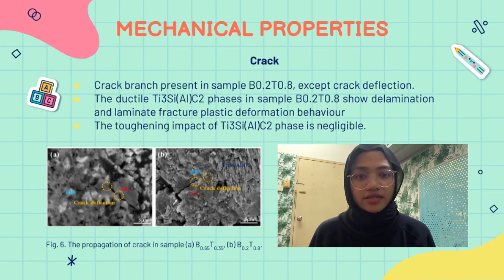The ductile Ti3SiAlC2 phases in sample B0.2T0.8 show delamination and laminate fracture plastic deformation behavior, which promotes crack branching and consumes a lot of energy to prevent crack propagation. The amount of Ti3SiAlC2 in sample B0.2T0.8, on the other hand, was limited and clumped together as a cluster. As a result, the toughening impact of the Ti3SiAlC2 phase is negligible.